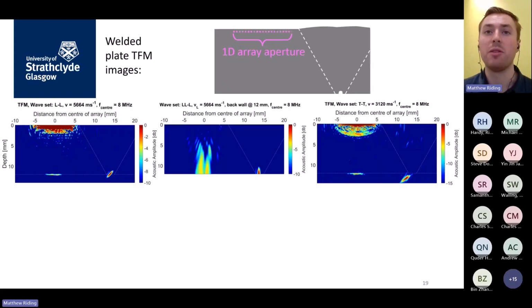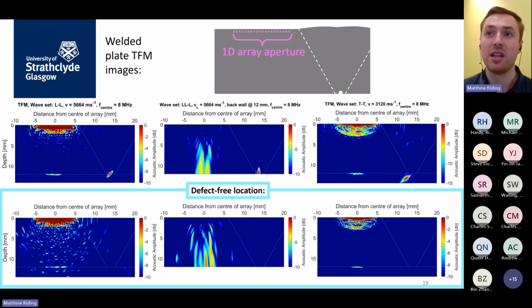It was good to see that when we moved further down the weld to a nominally defect-free area, those indications at the root of the weld all disappeared, and so that's nice evidence that we were genuinely detecting the presence of the defect.